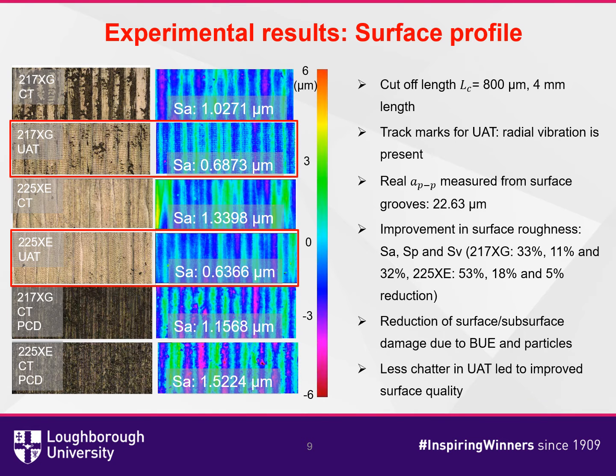The machined surface profiles were taken using a non-contact surface analyzer. The raw images are shown on the left, and depth profiles using the cutoff length of 800 micrometers are shown on the right. For UAT, track marks in the raw image show the radial vibration is present. The distance between each mark was measured to be 22.63 micrometers, showing slightly dampened vibration compared to free vibration, which was 28.8.